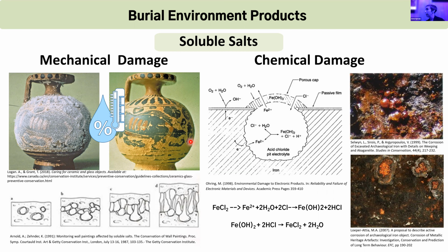And if there are any hydrogen ions in the mix, which there are in water, you're going to very quickly get yourself some hydrochloric acid. And this hydrochloric acid will then start to digest your artifact, often in these little pockets that you see. And as these pockets grow, they become very self-sustaining. They become that catalytic, self-sustaining acid production force.